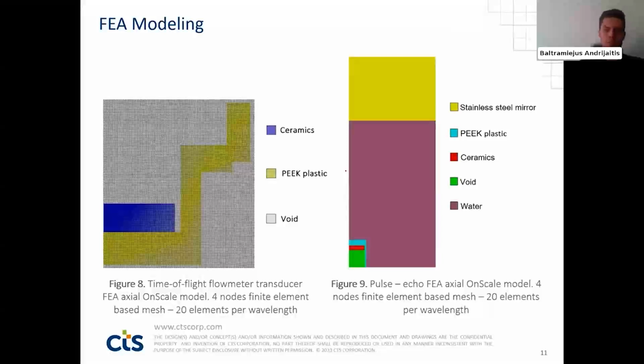Parallel to assemblies, an axial symmetrical model was created using the same on-scale software. The first one, you see it on the left, is for transducer impedance response definition, and the second, you can see it on the right, is to record the pulse echo response to evaluate overall performance and compare with the real samples. For the second model here, the mesh was chosen not to be shown because distances there are quite high. It's approximately 16 millimeters, and the image would be basically black with the mesh.